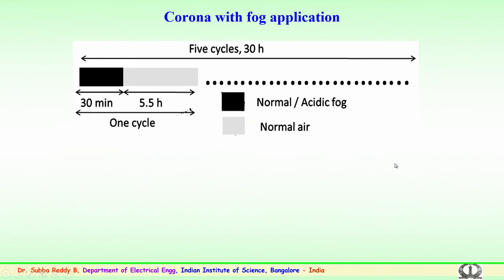So, how the cycle is designed: the application of voltage, and the application of fog, which could be a normal fog, a mist, or an acidic fog which contains acidic components that simulate acid rain. This methodology is adopted depending upon the number of hours. The cycle presently shown is for a 30 hours period. For example, the experiments have been conducted up to 100 hours also. If it is 30 hours, initially 6 hours is considered as one cycle.